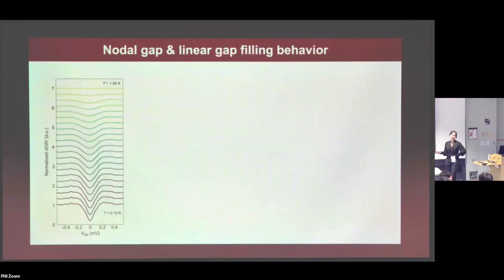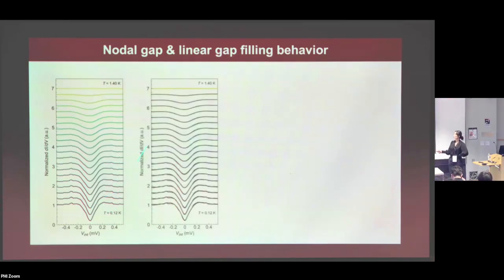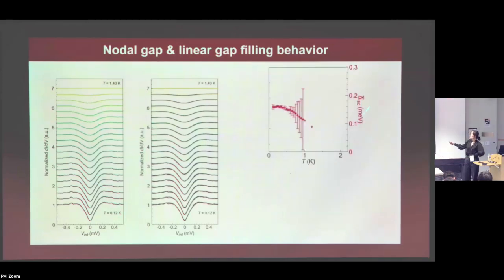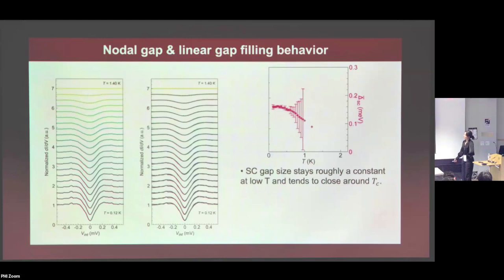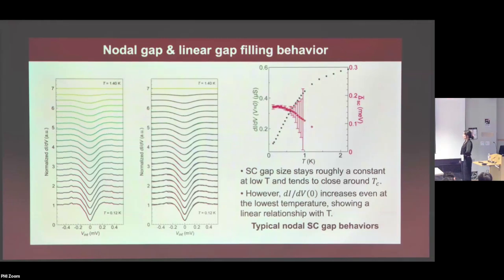So we can do further measurements, now increasing the temperature and looking at how the superconducting curve changes. These are the normalized curves. You can fit the superconducting curve with the nodal gap that we used in the previous slide, and then plot the magnitude of the gap size as a function of temperature. You can see that up until TC there's not so much change in the gap magnitude, but around TC it suddenly drops. In contrast, when you track the zero bias density of states, it immediately fills in, and linearly fills in exactly up to TC.